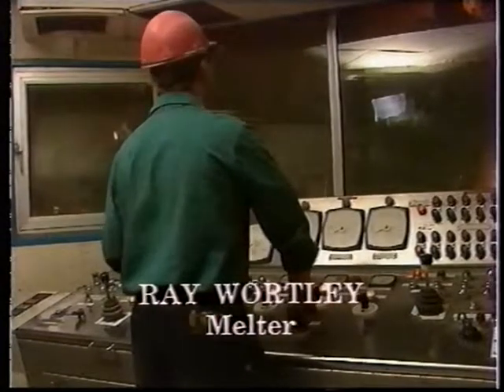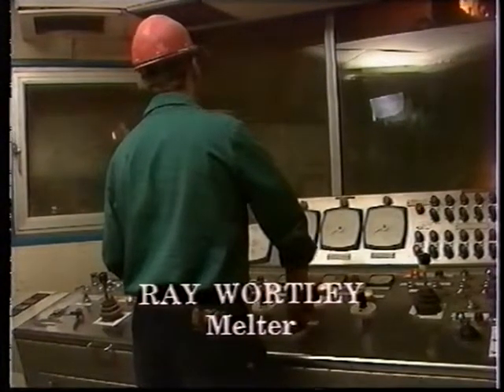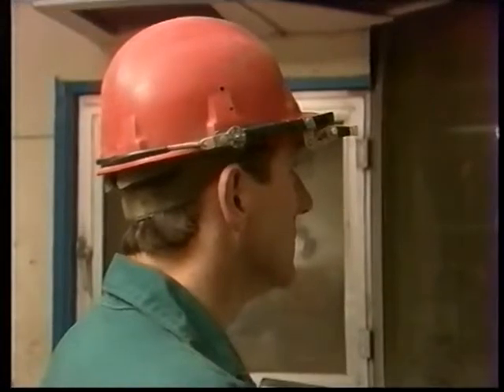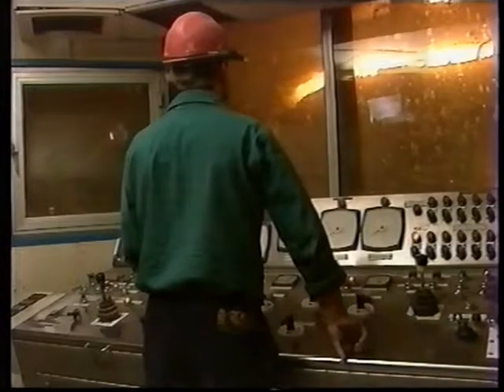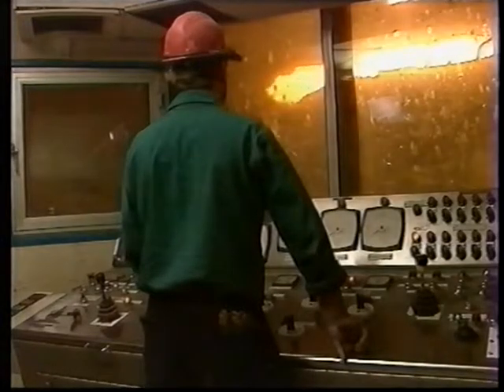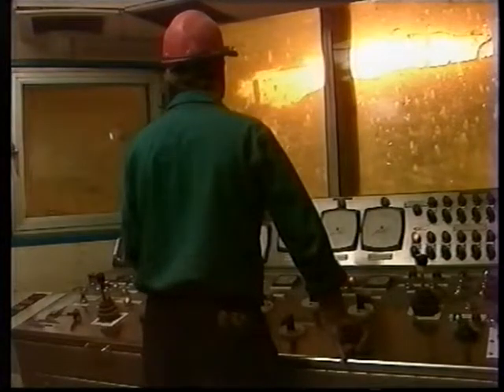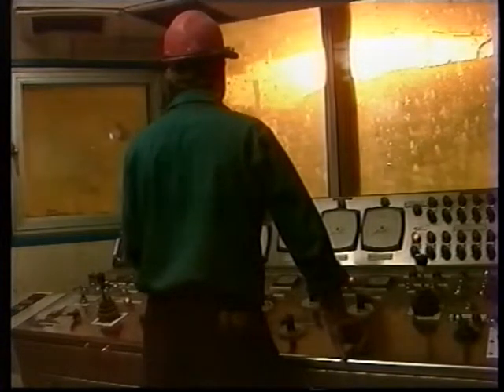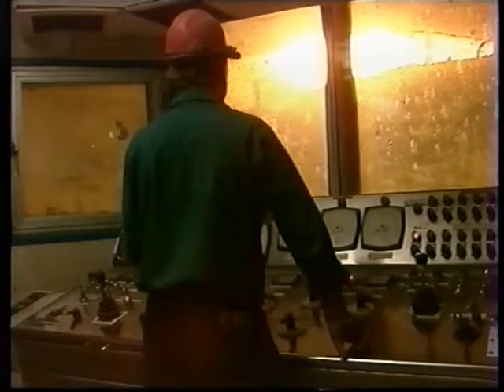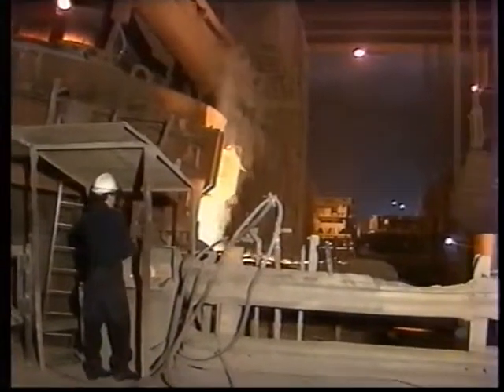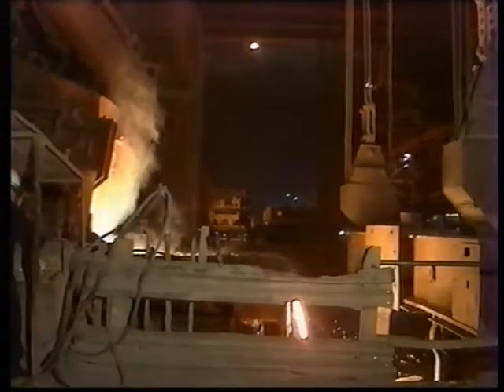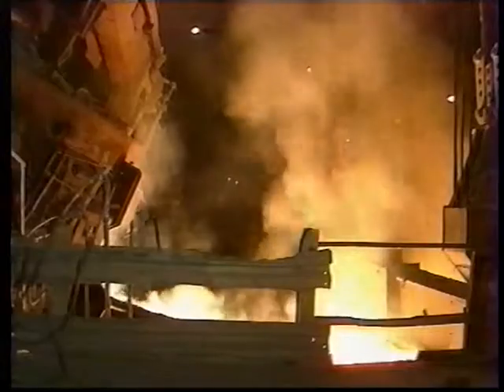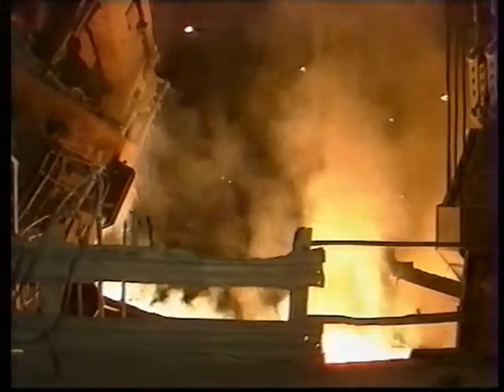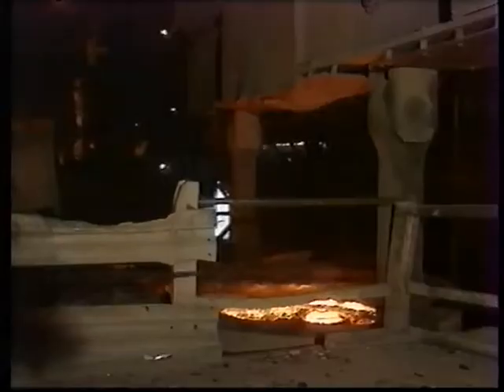This is where we melt the steel. We use 3 electrodes to create an arc to melt the cold scrap to a semi-fluid state. We inject oxygen to bring the temperature up to 1620 and the silicon down to a desired level for tapping to the AOD. When the charge has been melted to the required temperature, which normally takes 1.5 hours, it is tapped into the ladle for transfer to the AOD vessel, and a sample is taken for analysis.